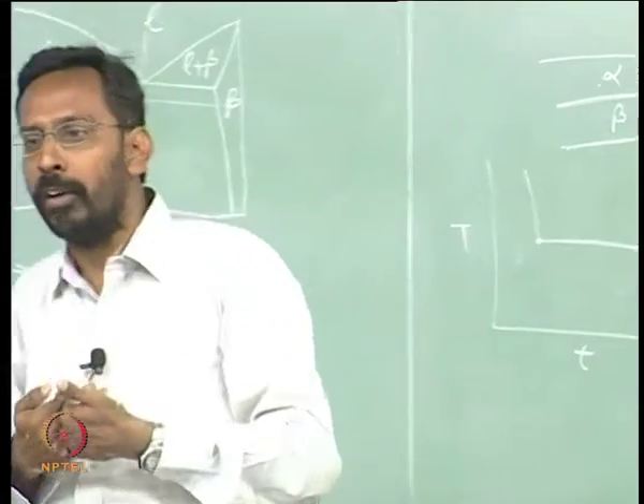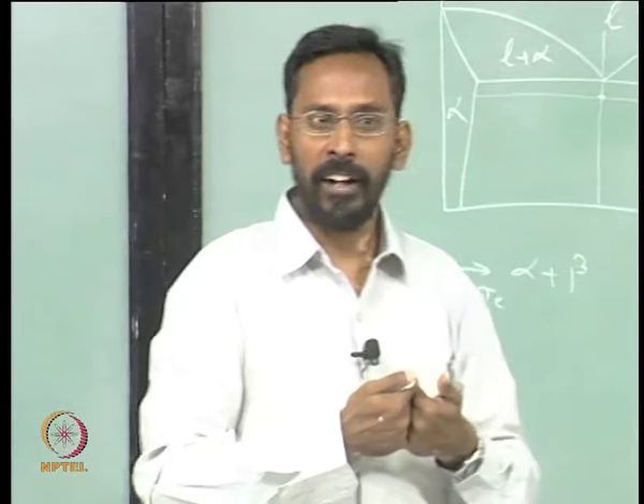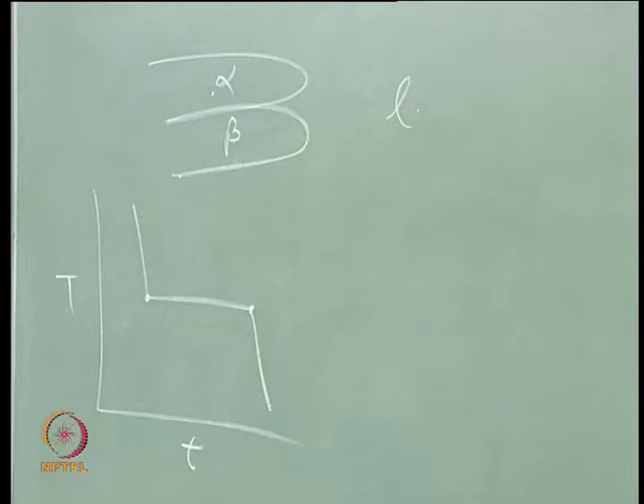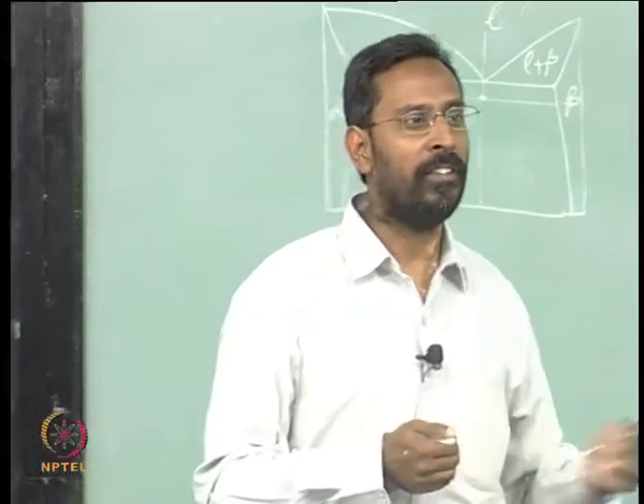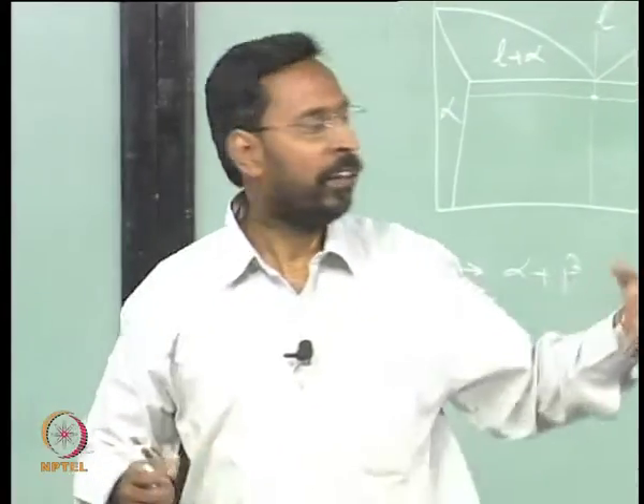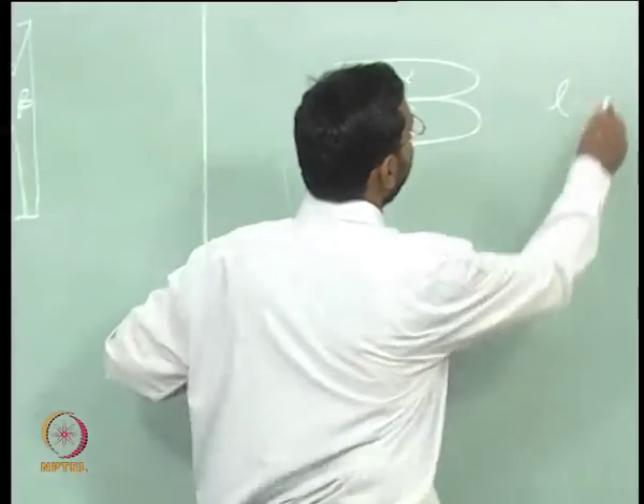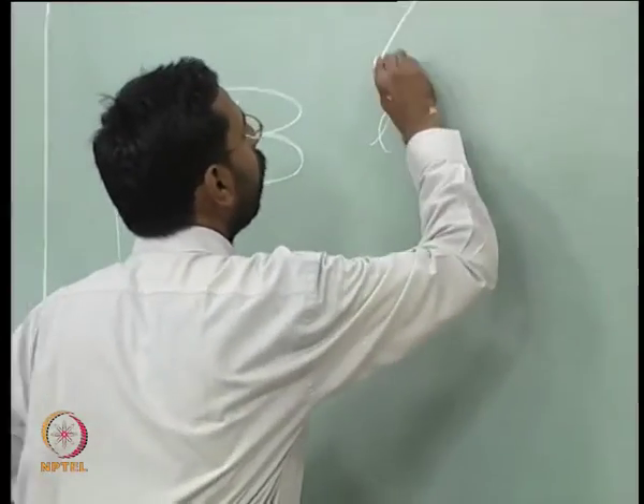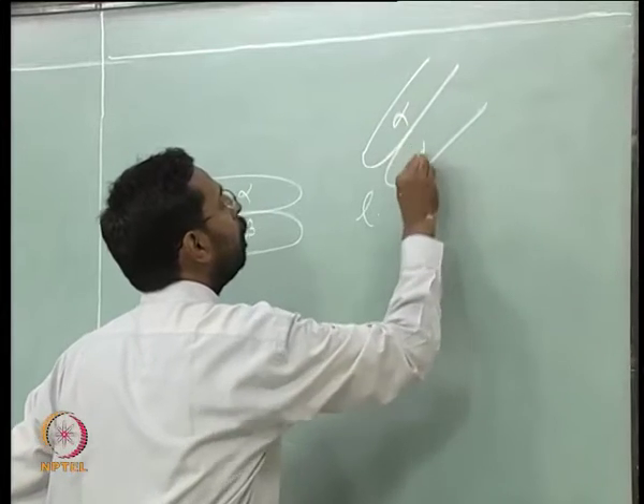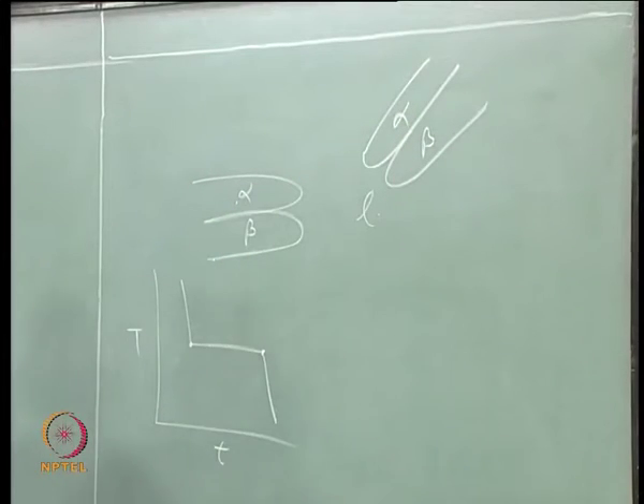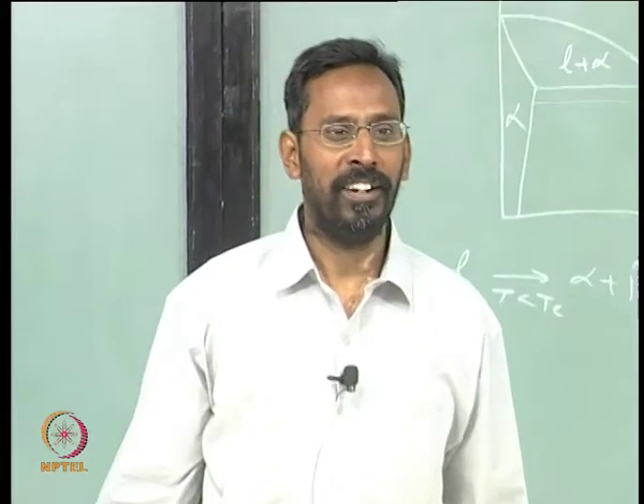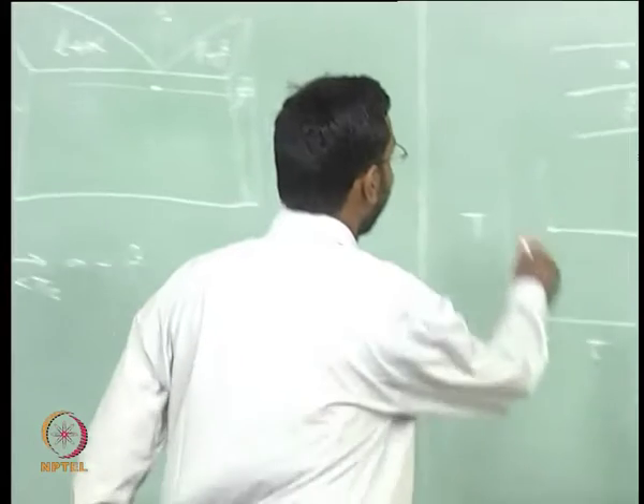What do we call those boundaries as? They are not grain boundaries. In a eutectic you do not call them grain boundaries, because a grain boundary is related to one single phase, and there is no one single phase here. So what do you call it when this nucleates here and somewhere else you have something else nucleating here, alpha plus beta, both of them come together and meet each other, what do you call that boundary? Of course, it is an interface. Even this is also an interface.